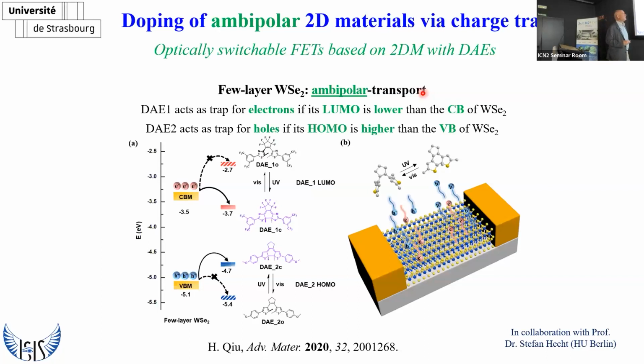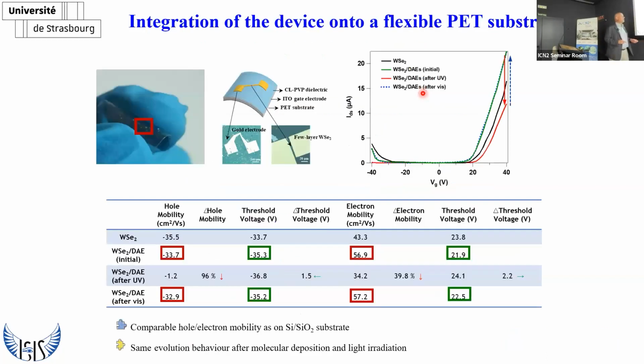In this study, we physisorbed a blend of two different diarylethenes. One is the very same that we used before, used to trap and untrap electron transport, whose energy levels are designed based on the conduction band of the tungsten diselenide. And the second one is another diarylethene such that its HOMO level is in the band gap of the semiconductor in the closed state, and out of the band gap in the open state. To make the long story short, upon illumination with UV light, we can bring both into the closed state and create traps, such that we can decrease the hole mobility by 96% and the electron mobility by 40%, which are totally recovered upon illumination with visible light.